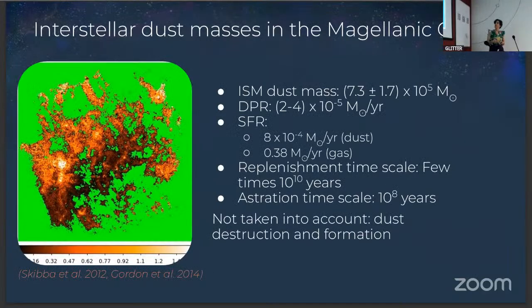Also, locally in the Magellanic Clouds and in many other environments that people have looked at in the solar neighborhood, we are not able to reconcile the dust production by evolved stars and supernovae with the interstellar dust mass. For example, one of the outputs of the SAGE survey of the Magellanic Clouds is that the interstellar dust mass is of the order of 7 times 10 to the 5 solar masses. The dust production is a few times 10 to the minus 5 solar masses per year. And the star formation rate is a few times 10 to the minus 4 solar masses per year. So from these numbers, you can calculate what the replenishment timescale is.